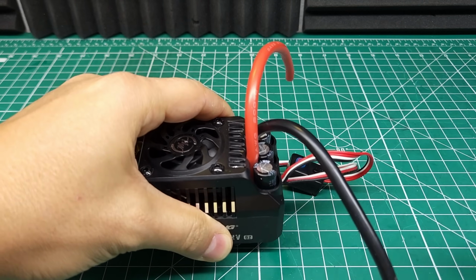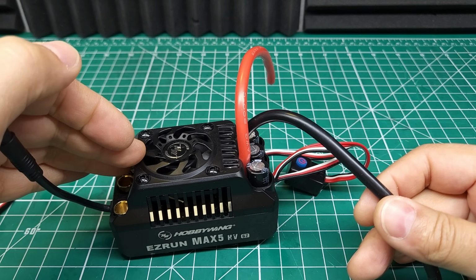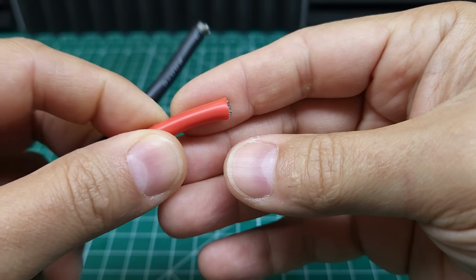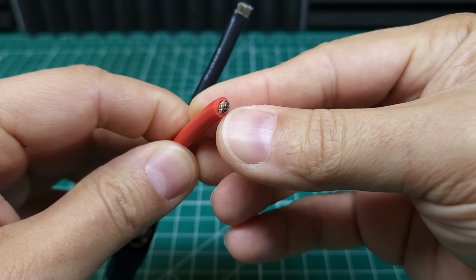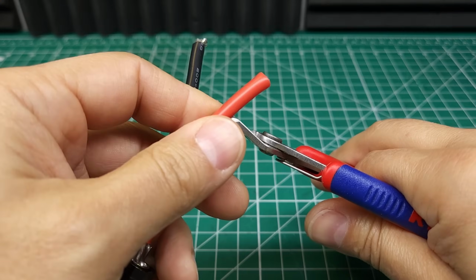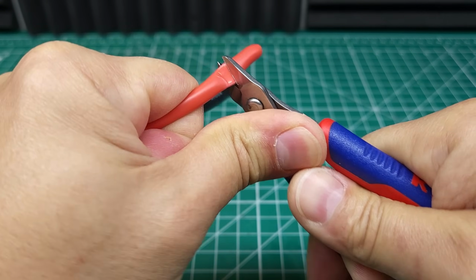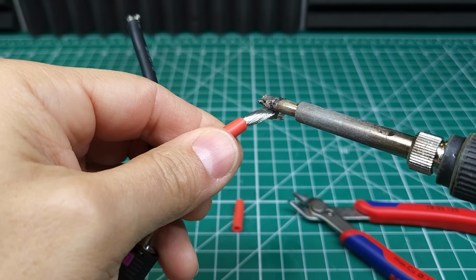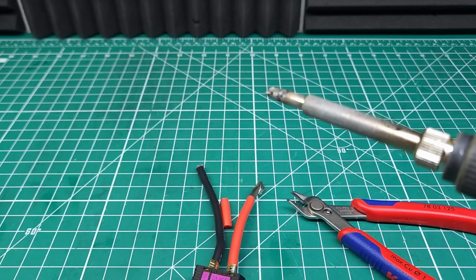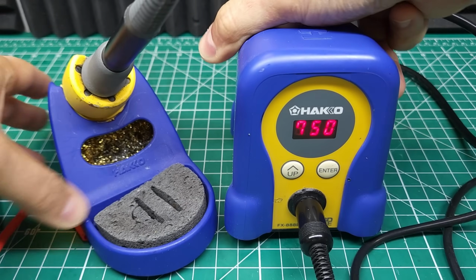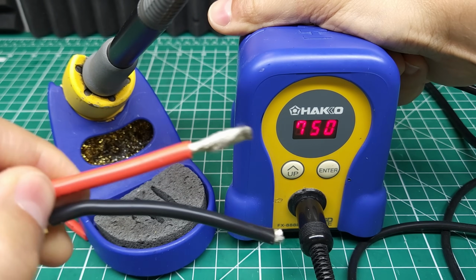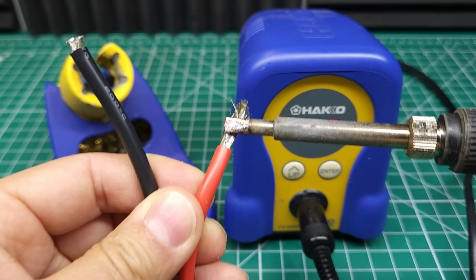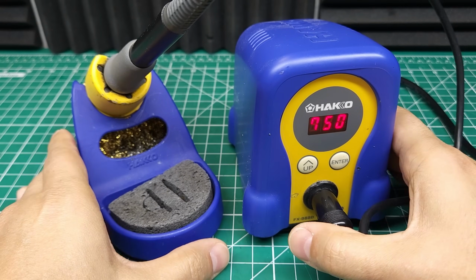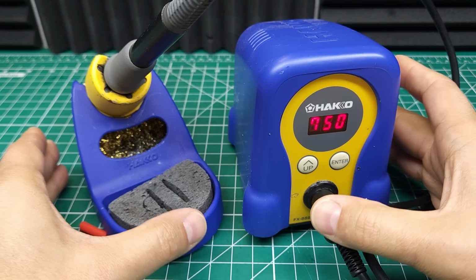And this is where we're starting to run into trouble with these modern giant ESCs and connectors. In order for the flux to properly clean and especially the solder to properly wet, the wire itself has to be hot enough. The problem with this is that electrical conductors are also generally really good heat conductors. And what happens when you take this iron and stick it onto the metal is it immediately starts pulling heat away from the iron and down into the metal, and it starts getting hot. If your iron isn't powerful enough to dump enough heat into that wire fast enough, it's never going to get hot enough to actually wet with the solder. A typical soldering iron temperature for melting lead or lead-free solder is between 600 and 700 degrees Fahrenheit.